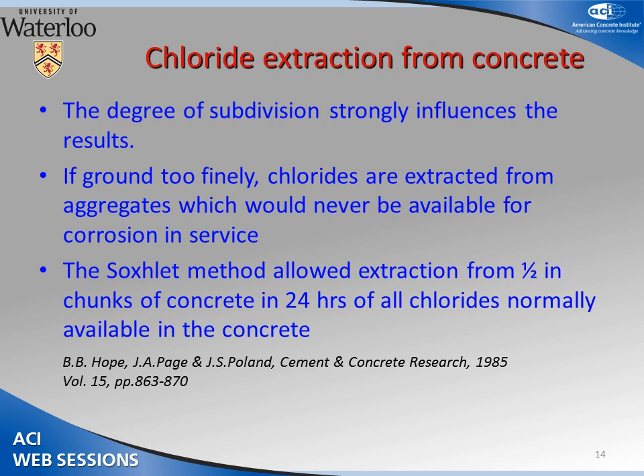Well, of course, if you think about concrete in practice, the aggregates are not ground, and yet in the lab, we grind them to get the chlorides out. So what he was trying to do was to figure out how much chloride was coming out of the aggregates, or would come out of the aggregates, and cause problems for the steel in practice as solid aggregate particles. So he introduced the Soxhlet method of extraction and found that you can extract from half-inch chunks of concrete all of the chloride that's going to be available throughout the life of the structure, predicted, of course, within a 24-hour period.